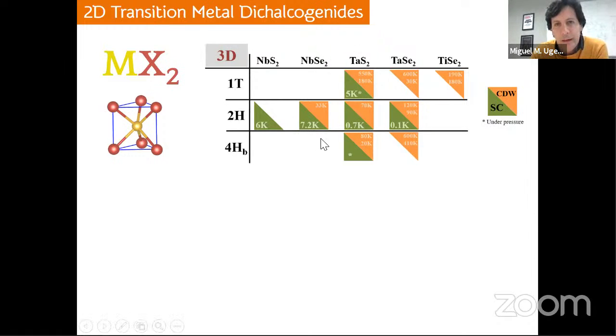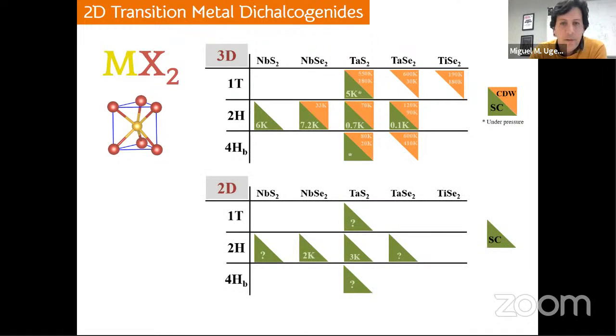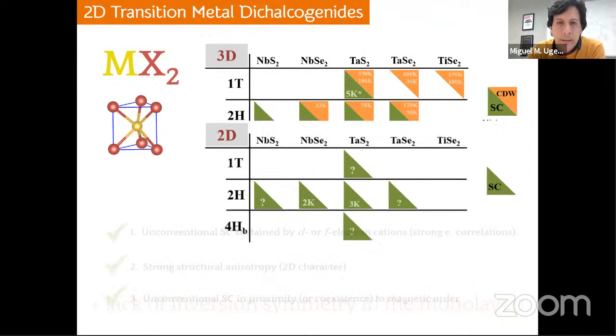For example, you have the case of niobium diselenide that has a superconducting critical temperature of 7 Kelvin, or the case of tantalum disulfide with a critical temperature of 0.7 Kelvin. In 2 dimensions, however, this field is still mostly to be explored. It's known now that niobium diselenide in the single layer form has a critical temperature of 2 Kelvin. Or, for example, a single layer of tantalum disulfide has a critical temperature of 3 Kelvin, but there are other materials that have not been studied. And of course, what mediates superconductivity is not known at all.